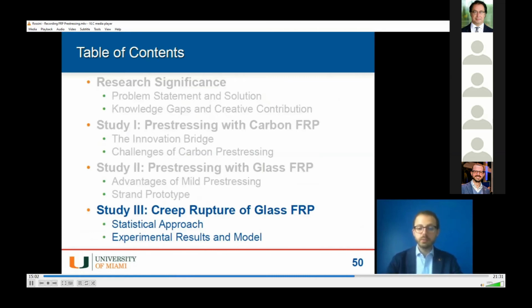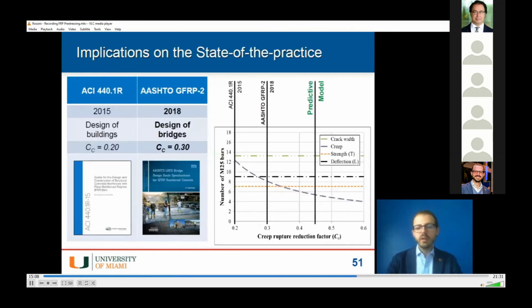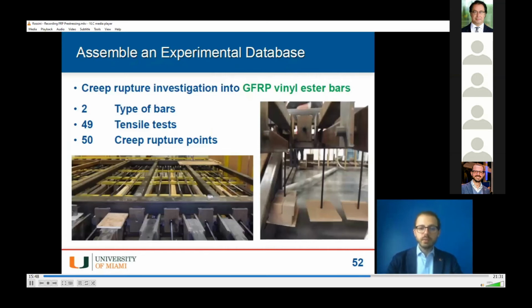In order to answer this question, we need to look into the creep rupture behavior of glass FRP. First of all, let's see where we were before undertaking this study. ACI was saying, and is still saying, that you can have a sustained load in your glass FRP reinforcement equal to at most 20% of the design strength of your material. We were able to raise this limit a little bit while publishing the second edition of the actual design specification in 2018, and we raised this limit from 20% to 30%. But now we will see that through this study, at least in some material systems, this limit can be as high as 45-46% of the design strength. In order to show this, of course, we had to conduct some experiments.